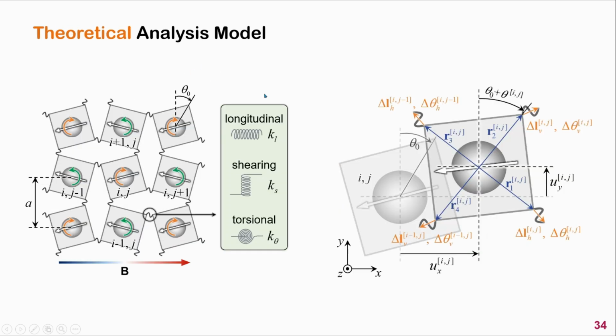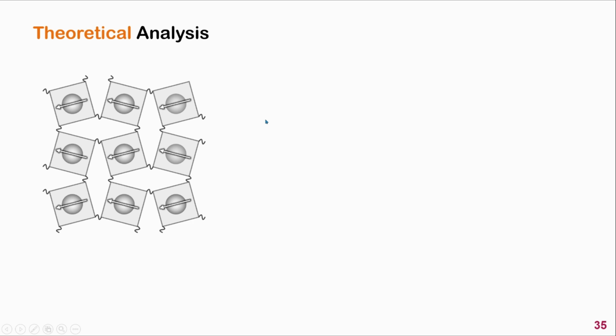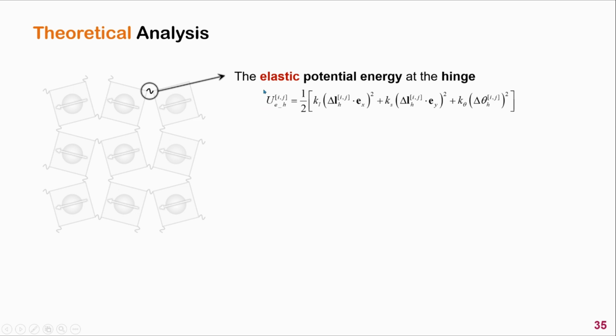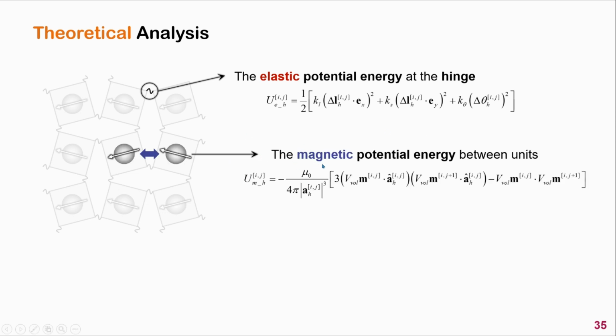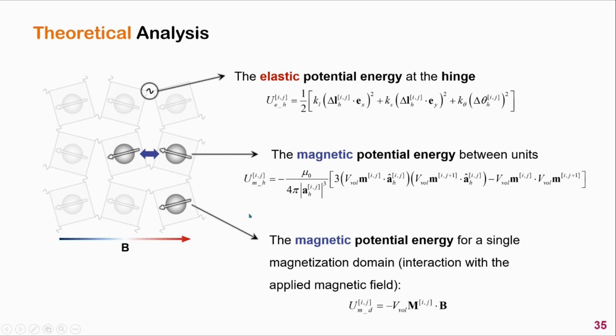In theoretical analysis, first of all, we need to express the deformation in these springs using the degrees of freedom of the square unit, which includes two translational components and one rotational component. The total potential energy of the system will be composed of three parts. The first part is the elastic potential energy stored at the soft hinge. There are three terms corresponding to the three linear springs, respectively. The second part is the magnetic potential energy that accounts for the interaction between neighboring magnetic cores. The last term is the magnetic potential energy that accounts for the interaction between a single magnetic core and the external magnetic field. Using the total potential energy, we can calculate the deformation of the system for given magnetic fields.